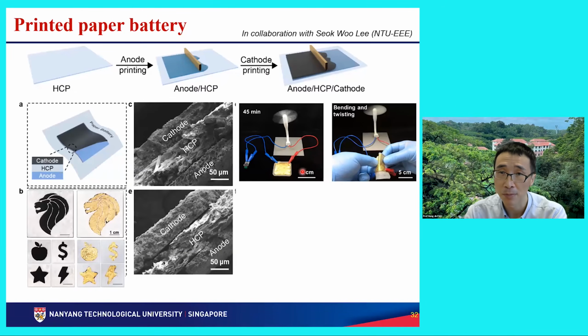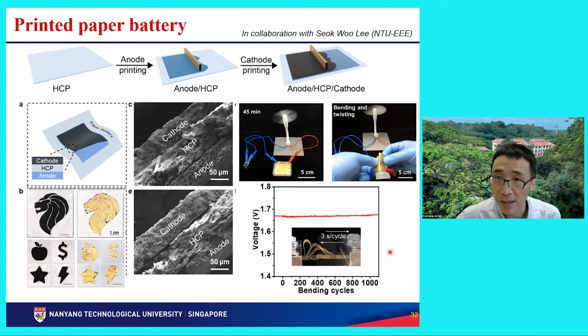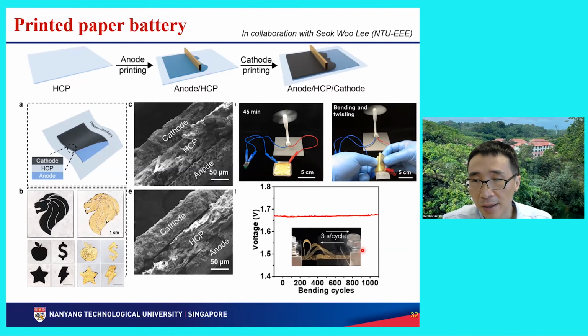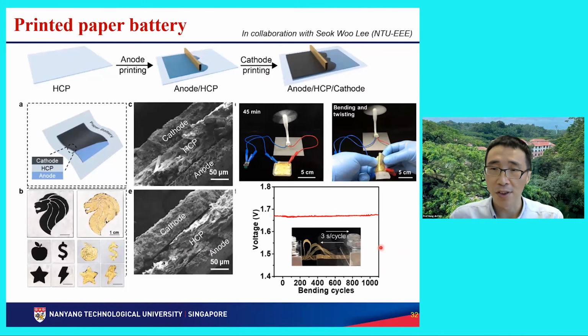Okay, we have an experimental demonstration. Cut in half, cut to a quarter, still working. No issues. For example, this is a bending test. During the bending test, you can monitor the voltage change after many bends. You can bend the thin film battery 1,000 cycles, and the output voltage has no big change.